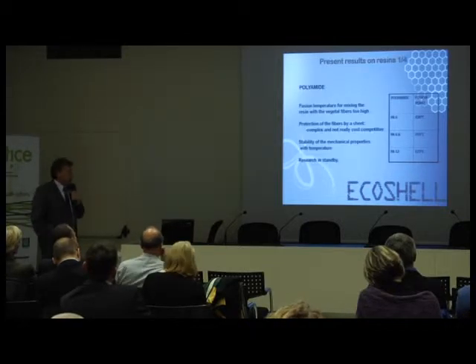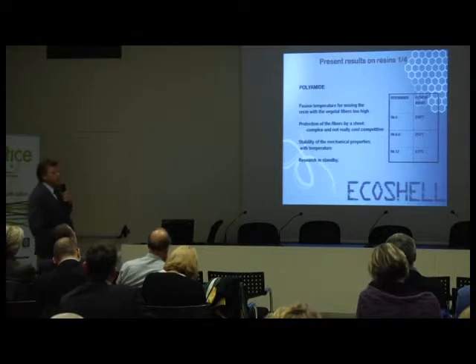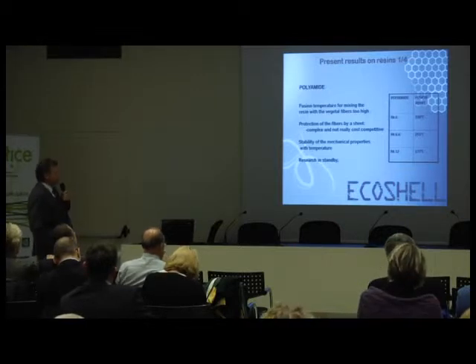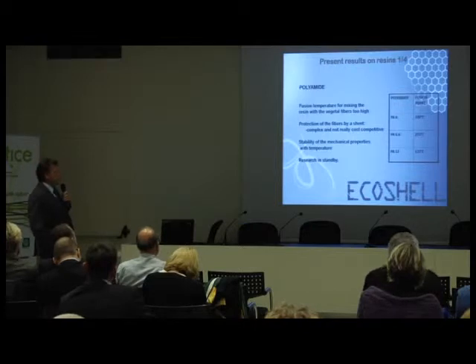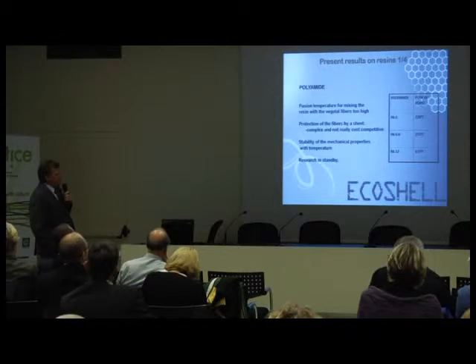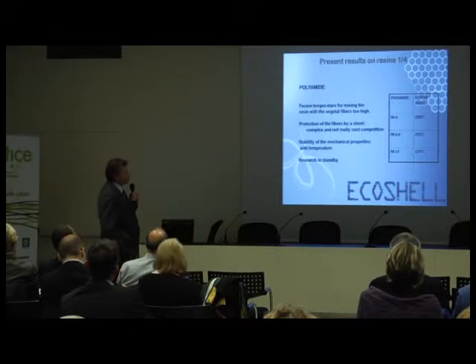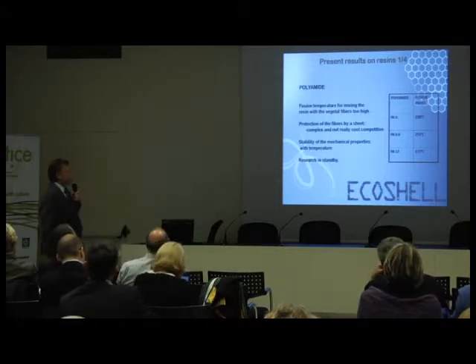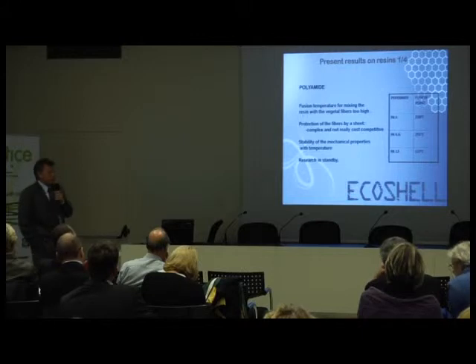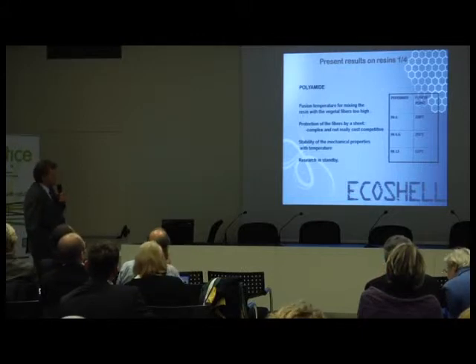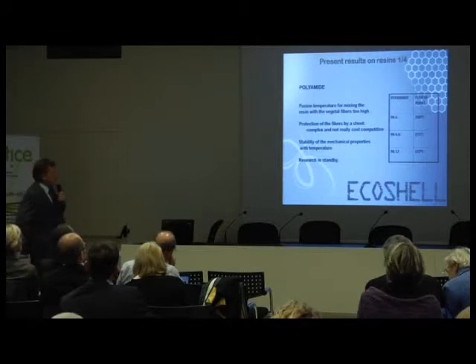For polyamide, we face a very important issue, the fusion temperature for mixing the resin with the vegetal fibers. Today, if you want very high mechanical properties of our composite, we need to have polyamide 6 or 6,6. And those polyamides have a fusion point at more than 200 degrees. So the vegetal fibers can't afford such a temperature. That is the reason why today we have some difficulties to have a good impregnation of the fibers by the polyamide.